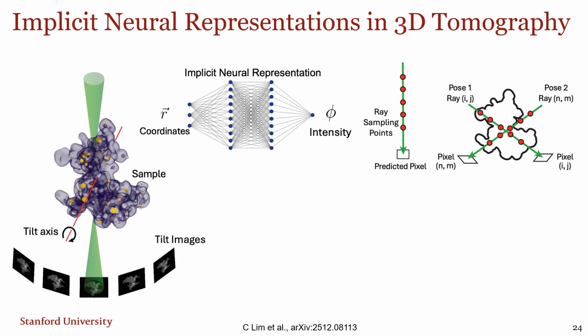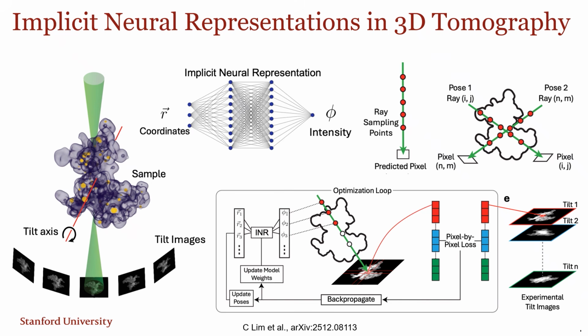So if you want to apply this to 3D tomography, you can imagine every pixel in our measurement is a ray that's tracing through our 3D volume. So we simply ask the network, what is the value here, here, here, here, sum it up in a projected vector, and that's what we compare against our experimental measurement. And then we use that to update our object weights here for the generator. And of course, we also update the pose of the object, the rotation, the tilts, and this makes a huge difference, as you're going to see.